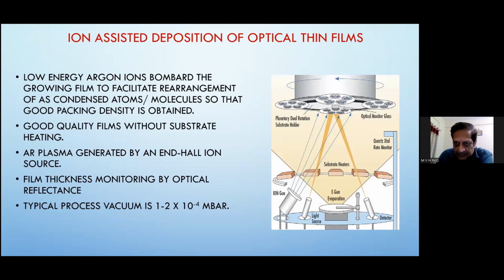Okay. Now, this is also ion assist deposition. I'll quickly go through it. It's basically the same as electron beam deposition. Only thing is, as I told, that to improve the process, we can impart extra energy by putting in an ion source. The purpose of the ion assist gun is, as shown in the earlier growth modes, suppose island growth is happening. If there is no ion gun, it will simply grow by island growth, and is a very rough surface. The surface will be very rough, and also a lot of porosity will be there. It will not be good.